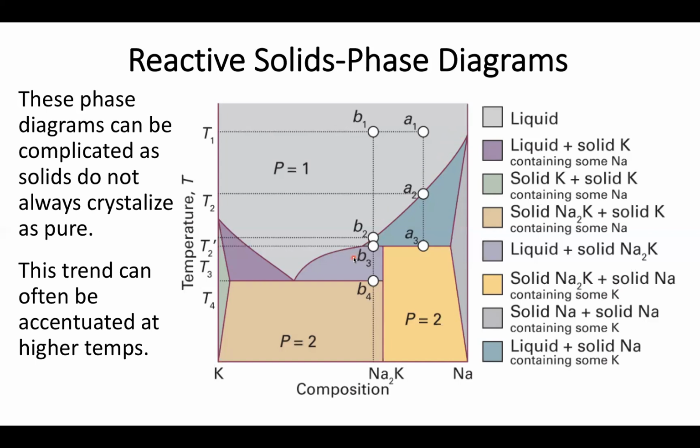So whenever you see curved lines, they often mean some form of fluid phase is part of the system, whether it's a liquid or a gas. However, when you start seeing a region that's essentially bounded by a curved line and a solid line as present here, here, and here, this is often indicating some form of being a two-phase region where you're generating a liquid and a solid. And again, while this rule doesn't always hold, it's a good kind of starting place to try and think about what may be present in these phase diagrams.